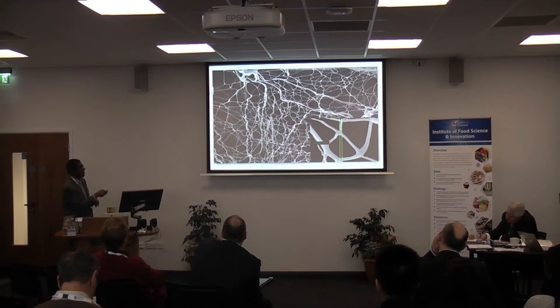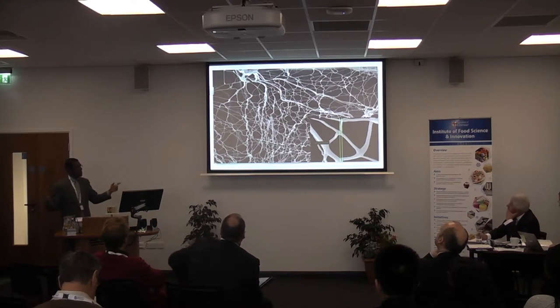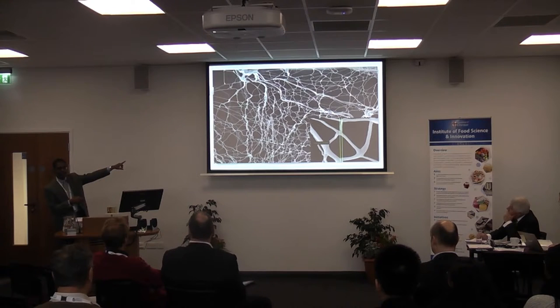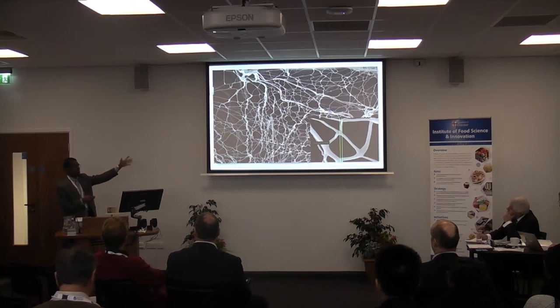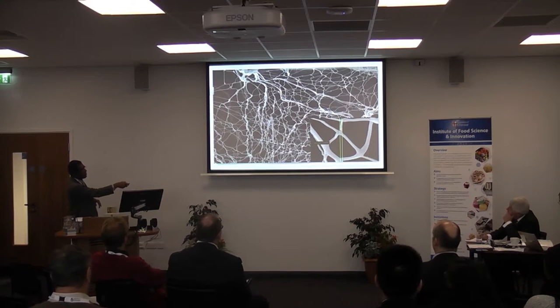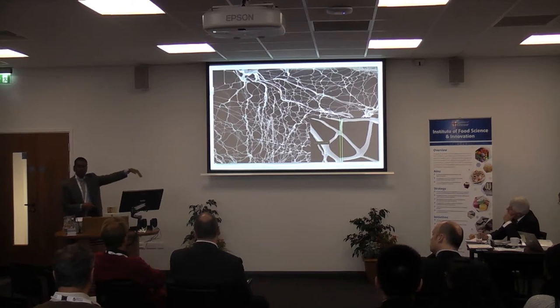And this is another one. This is actually a natural jelly material from a natural food. It has been practiced for the last 4,000 years, but it was never reported that this is a nanoscale material. This has been reported as a micron, 100 microns or 500 micron fibrous structure. We found out that it is not 500 micron, it is nanoscale. When you look through a high resolution microscope, you can see it is 50 nanometer. The smallest fiber is 50 nanometer. This is a typical gel structure under the microscope.